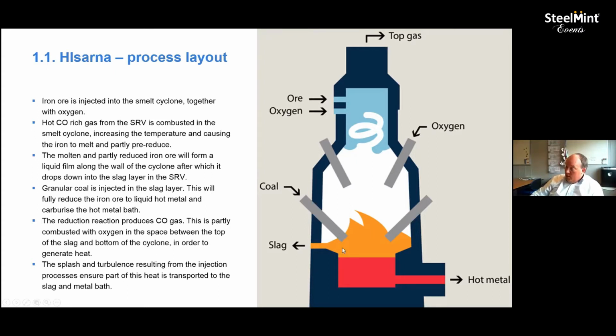Like I said, carbon monoxide gas escapes here and is then partly post-combusted in this section here, because the reduction reaction, of course, costs energy, which means that if we wouldn't add temperature, we would lose heat and the whole situation would solidify. The turbulence here makes sure that the combustion heat is assimilated in the slag and the hot metal, and that's how we keep the hot metal warm. Temperature of the hot metal about 1400, 1450, slag about 20 to 30 degrees hotter than that.